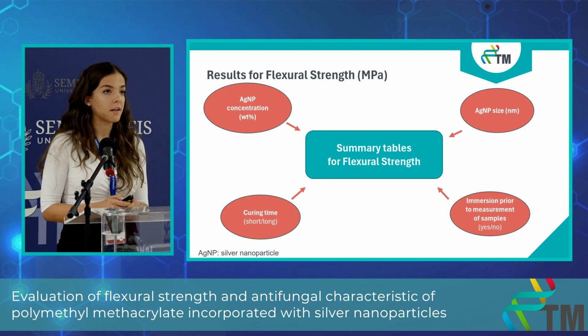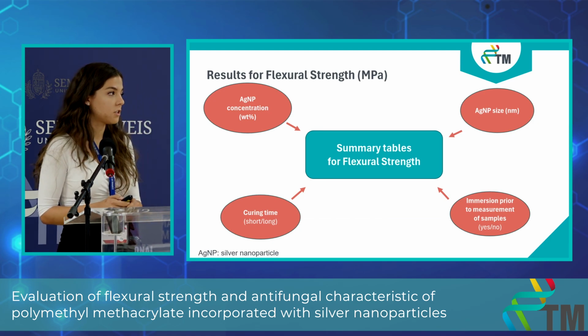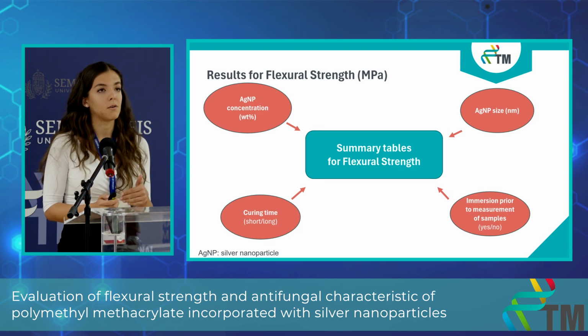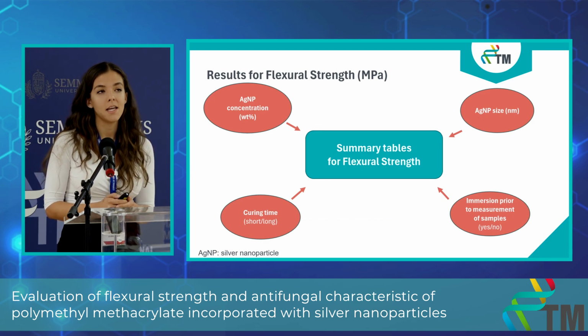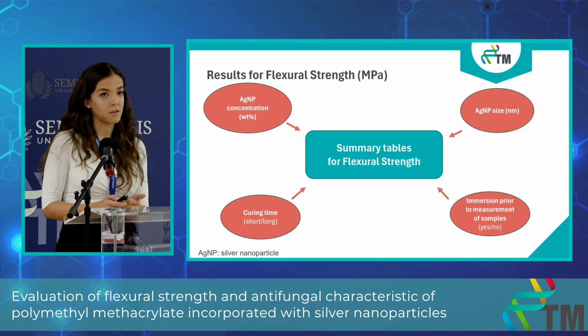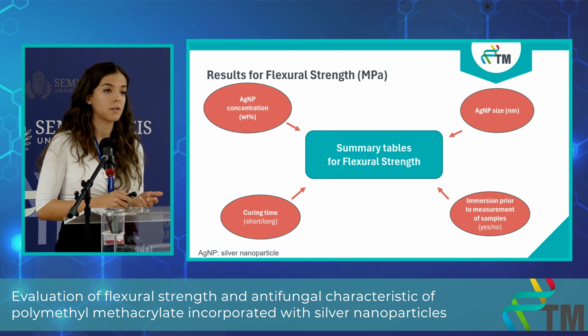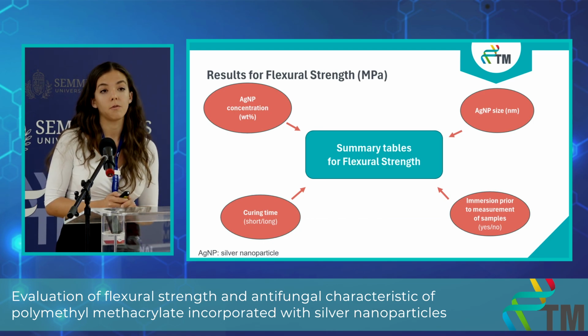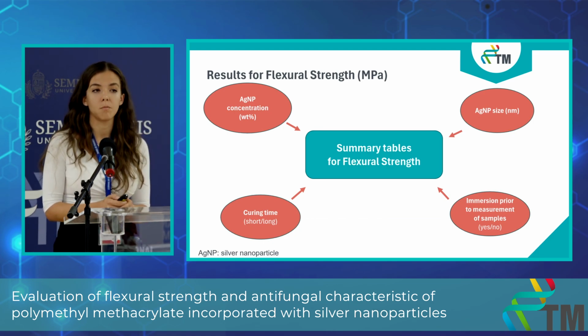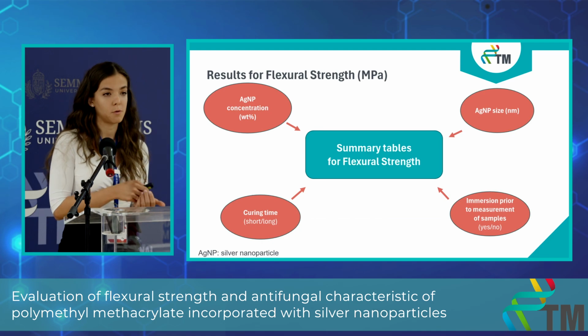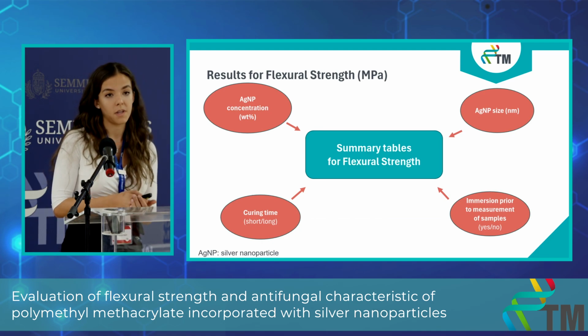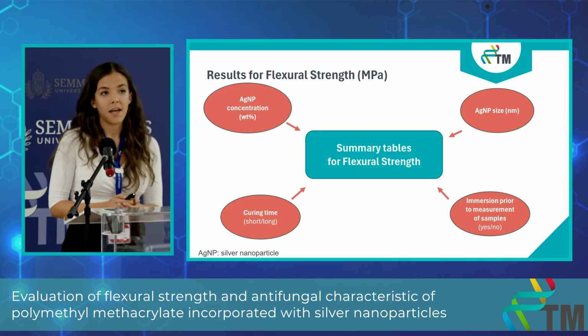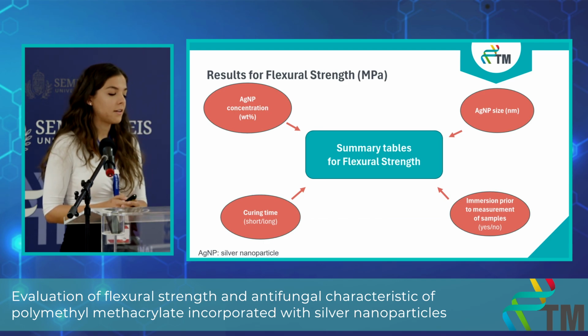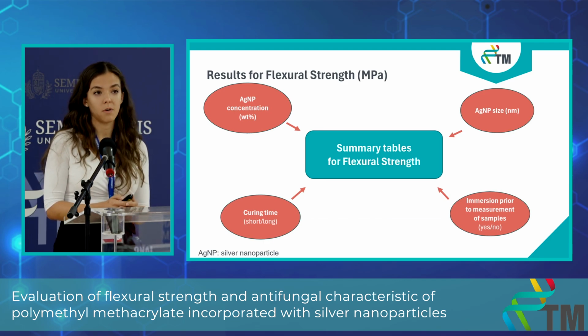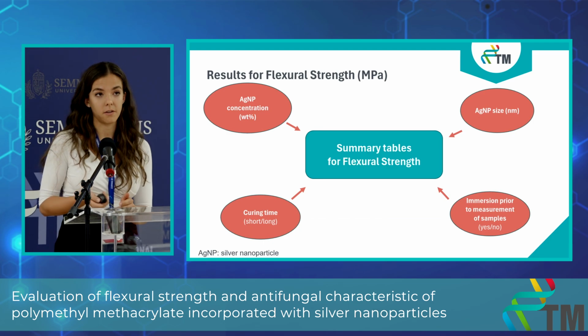In the eligible articles, 4 factors were mentioned which have an effect or modify the flexural strengths. These were the silver nanoparticle concentration, the silver nanoparticle size, the curing time, whether it was short or long polymerization, and the fourth was the immersion of the samples, whether they were immersed right before the measurement in water for 50 hours or not immersed. And we made multivariate analysis and we included all these factors.